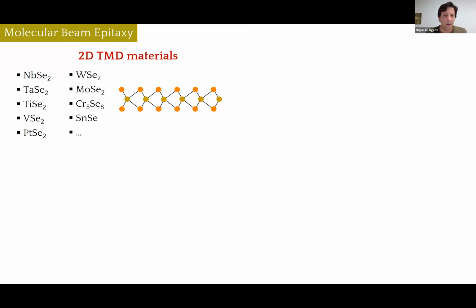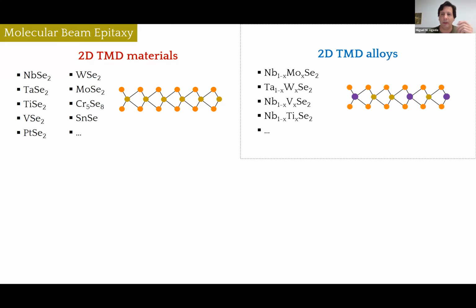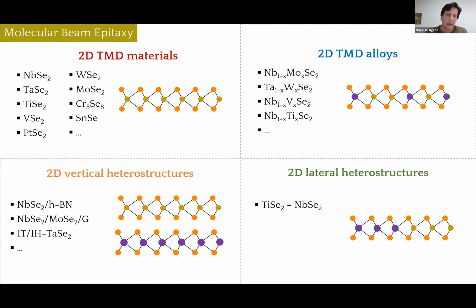But we can go beyond these materials. For example, I will show you today that we've been able to grow 2-dimensional TMD alloys, mixing, for example, 2 different transition metal elements. And also we can grow heterostructures, vertical heterostructures, such as the one I'm going to focus on today, the 1T over 1H, or 2-dimensional lateral heterostructures. Today I will show you results about 2D materials, TMD alloys, and vertical heterostructures.